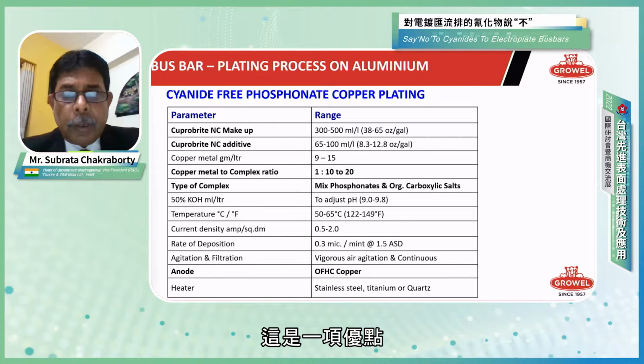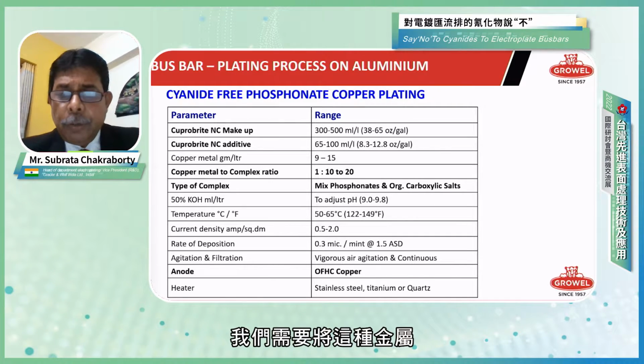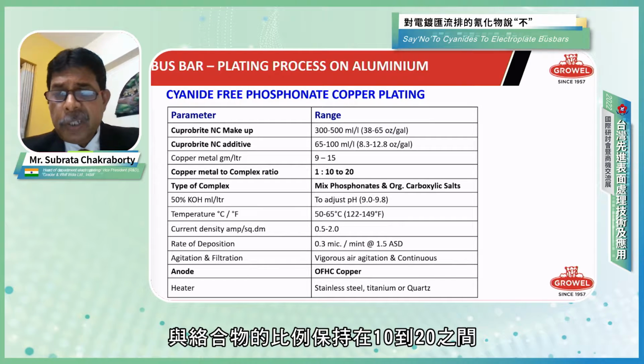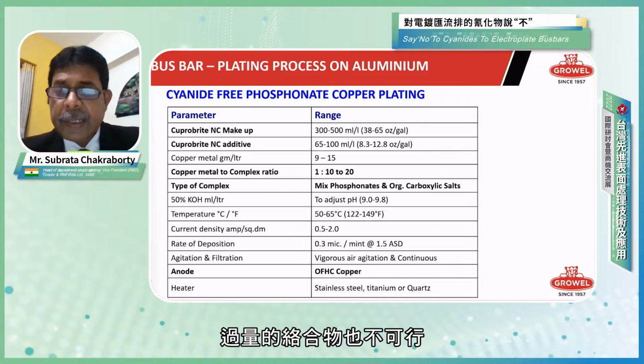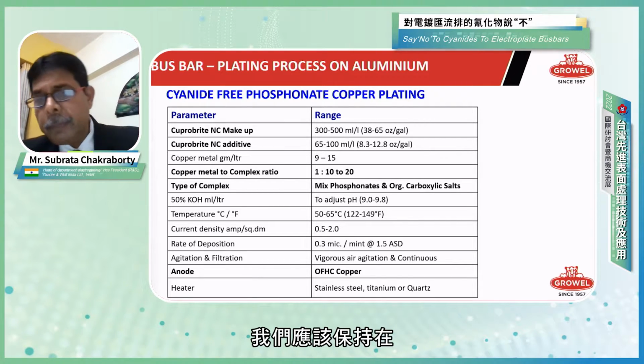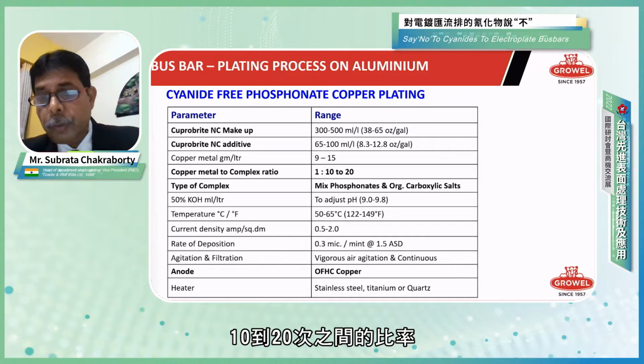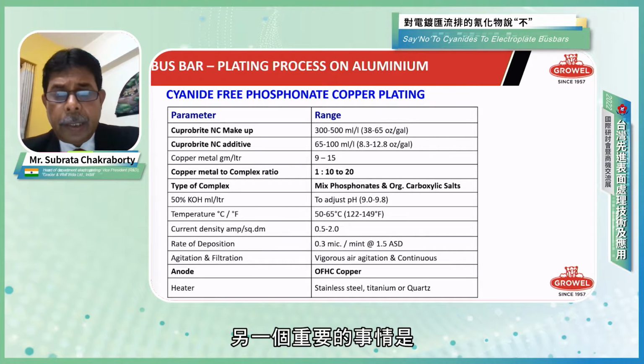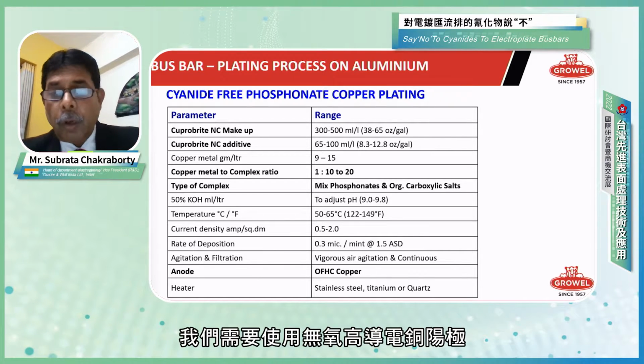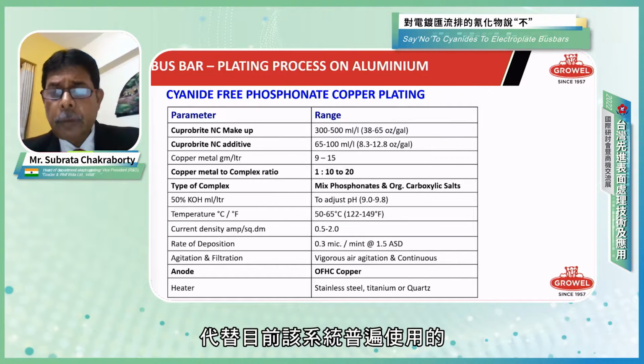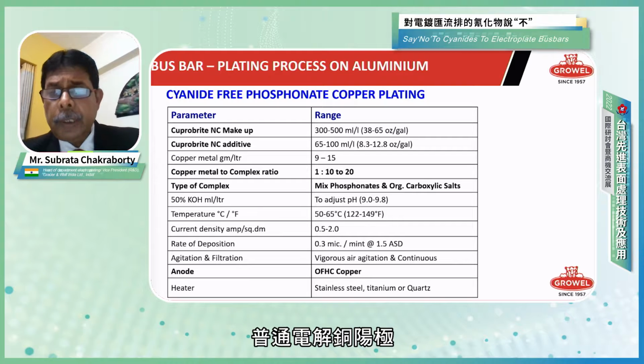This is one advantage, and we need to maintain this metal to complex ratio at 1:10 to 20. A very excess amount of complex is also not desirable, so we should maintain somewhere between that 1:10 to 20 ratio. Another important thing is that we need to use oxygen-free high conductive copper anode in place of normal electrolytic copper anode, which is popularly used so far with the cyanide-based system.